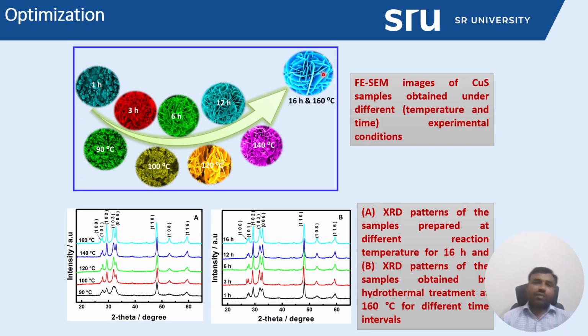So in order to confirm, we have verified different conditions. We had the same hydrothermal reaction and similar conditions, but followed a different time interval, and then the collected product was verified by FESEM, similarly for different temperatures. So from 1 hour we have performed up to 12 hours. See here, increasing the time: 1 hour, 3 hours, 6 hours and 12 hours.